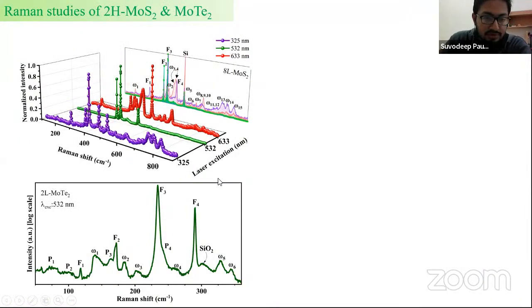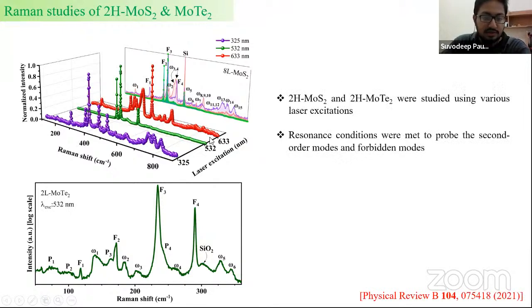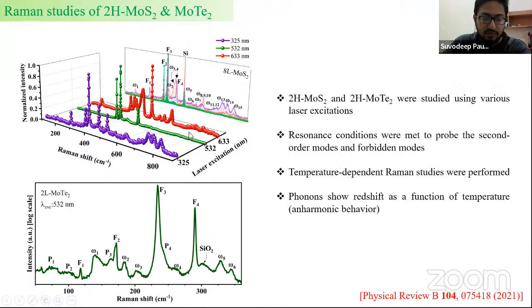So we went on to study the 2H phase again of MoS2 and MoTe2. We performed experiments with different lasers to probe the first order as well as the second and higher order phonons, mainly to probe the phonons at the Brillouin zone and also away from the Brillouin zone.